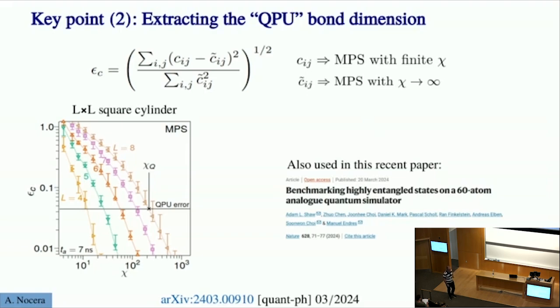Although I showed you before a very good agreement, if you look closely, there is of the order of a few % deviation between the expectation value of the QPU and the MPS result. So we could extract an indirect measure of the entanglement of this final state at the end of this non-equilibrium annealing process.